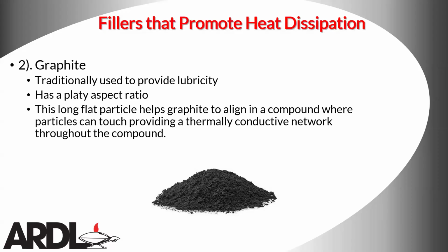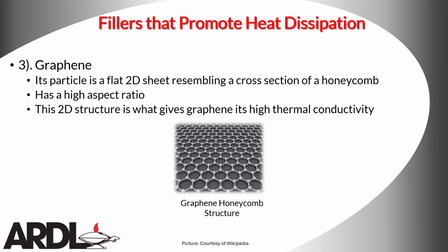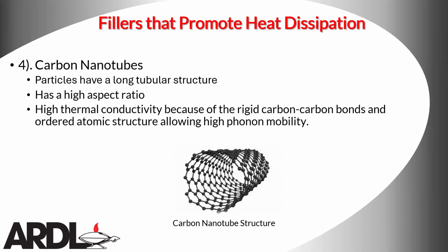network throughout the compound. The third filler is graphene, and its particle is a flat two-dimensional sheet resembling a cross-section of a honeycomb, and it has a very high aspect ratio. This two-dimensional structure is what gives graphene its high thermal conductivity. And then the last filler we're going to talk about today is carbon nanotubes. As the name states, the particles have a long tubular structure, and this tubular structure provides high aspect ratio, and it has high thermal conductivity because of the rigid carbon-carbon bonds and ordered atomic structure, allowing for high phonon mobility.